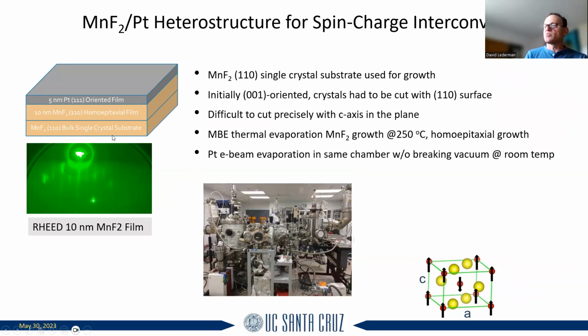Okay, so this is the film. This is what the sample looked like. We started out with a single crystal, and the key here is having a very clean interface between the non-magnetic heavy metal film and the antiferromagnet. So we grew another layer using MBE to get a clean interface, and then we grew the platinum on top. And the idea is that with a single crystal we could not only do the spin Hall effect, but also a resonance experiment, and by measuring the absorption make sure that we're actually hitting the resonance of the antiferromagnet like we're supposed to.